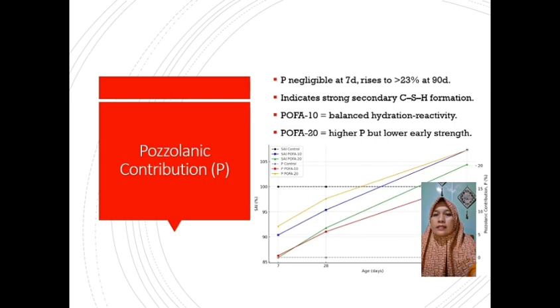This progressive increase demonstrates strong long-term pozzolanic activity as silica in POFA reacts with calcium hydroxide, producing additional C-S-H gel that densifies the matrix.